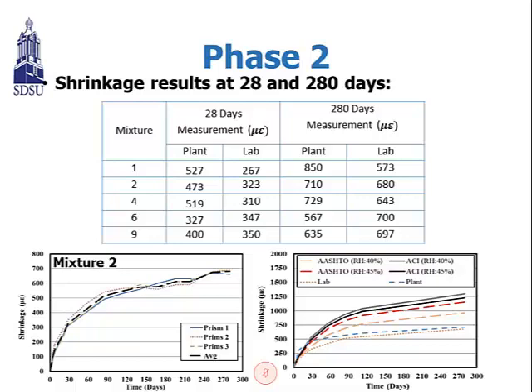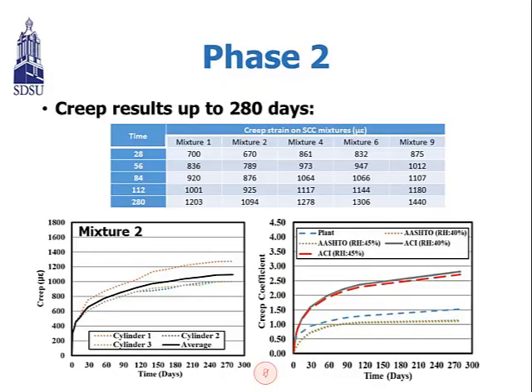And here's the creep result. We measured the creep strain up to 280 days. And you can see the table, the times we measured, 28, 56, 84, 112, and 280. And as I said, we have five mixtures, and you can see some difference in the creep result. Also I selected one mixture, which is mixture two, as shown in the figure. And each mixture, actually I didn't mention, has three cylinders, and then we average them to show in the table.